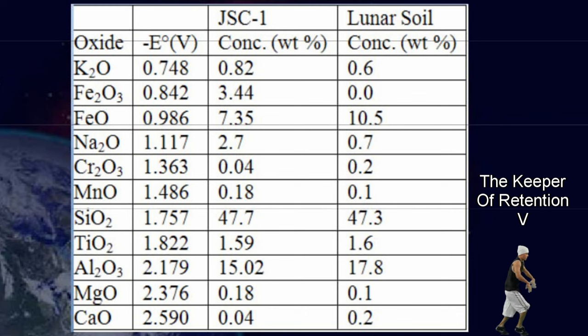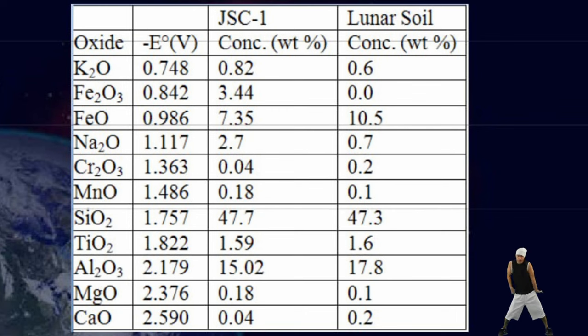But this 0.8 volts will not be enough to free the iron from the iron oxide. If you raise the voltage to 1, you should be able to free the iron, which will deposit on the cathode. And so, voila, you have iron, which you can remove mechanically by either draining it or changing the cathode with a fresh, new, clean one. At 1.2 volts, you get sodium. At 1.4, you will yield chromium, and so on.